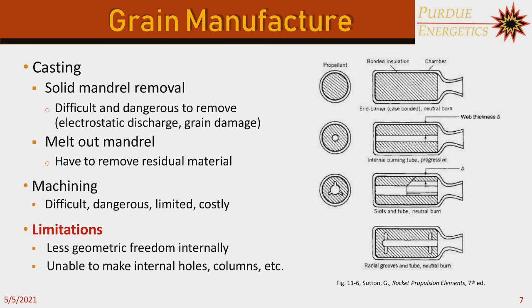More commonly, people will add a central port to their motor. So that's going to change your burning surface area over time as the surface regresses. The way that you make these central ports typically is by using a solid mandrel to hold that space. So you will insert the mandrel into your motor grain, and then you'll pour your propellants around that. And then after your propellant slurry crosslinks, then you remove the mandrel, and that's how you get your core shape.